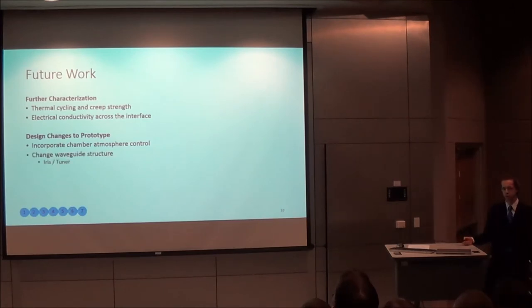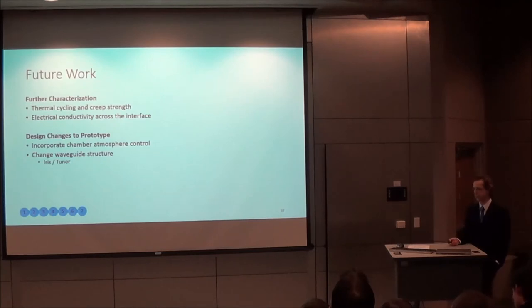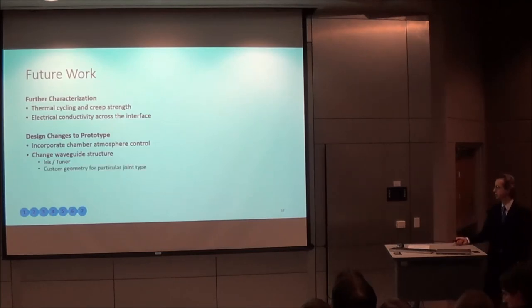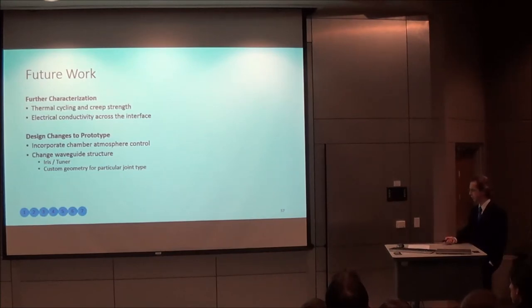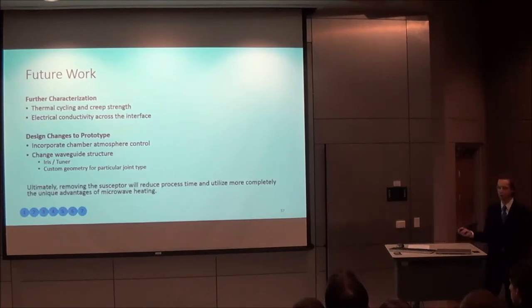Changing the waveguide structure could improve coupling of the target to the wave by use of perhaps an iris or a tuner, a three-stub tuner. Custom geometry could be used in the waveguide for each particular joint type to improve that coupling. Ultimately, though, removing the susceptor will reduce process time and really utilize more completely the unique advantages provided by microwave heating.